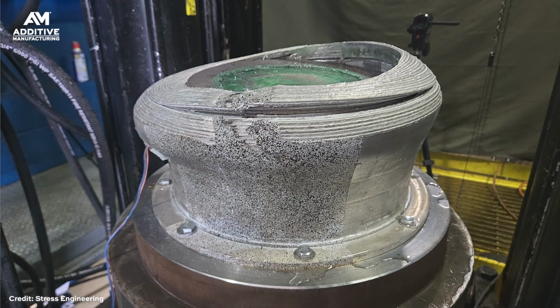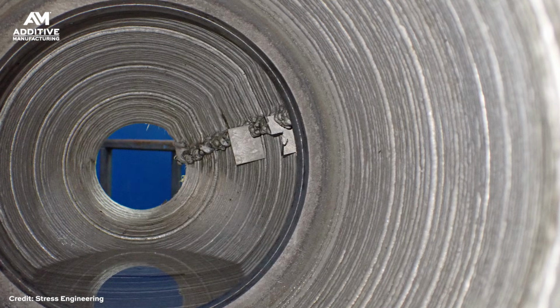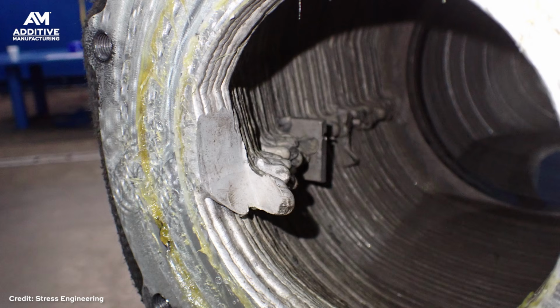But you might have noticed something interesting. When it compressed, it did not compress evenly all the way around. That was due to a change in geometry or stiffness of the actual part itself. So if you had seen the ID of the part, there was a stop-start area that was thicker than the rest of the part. And so that thicker part was a little bit stronger than the rest. And so the opposite side of that is what squished down first. And then the thicker part failed as the whole load came down across the part.